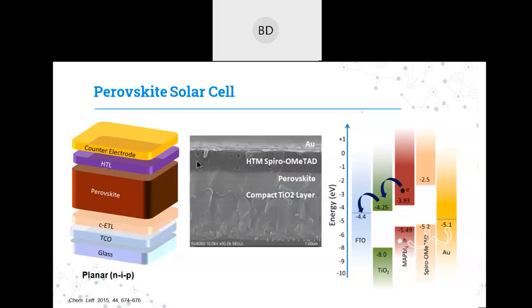If you see the scanning electron microscopy image of the perovskite solar cell, the compact TiO2 layer can vary from around 6 nanometers to 80 nanometers. The perovskite layer varies from around 300 to 700 nanometers, depending on the perovskite type that you are using. The hole transporting material is around 150 nanometers, and the gold electrode is around 60 to 70 nanometers. So these are the typical thicknesses used in solar cells.